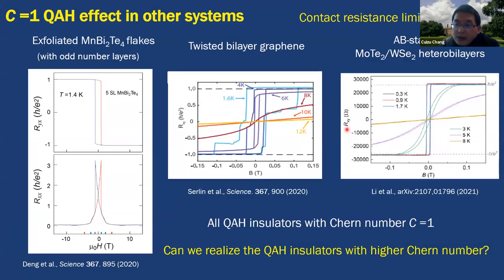We know that the quantum anomalous Hall effect is already realized in chromium and vanadium doped TI systems. In addition to these two systems, the C equals one quantum anomalous Hall effect has also been realized in these three systems, in the past 2 years. And in 2020, in the exfoliated intrinsic magnetic TI flake, which we call manganese bismuth telluride flake, with odd number layers, the quantum anomalous Hall state was realized at the ferromagnetic state. Also in twisted bilayer graphene, using interaction to make a gap, the quantum anomalous Hall state was realized.